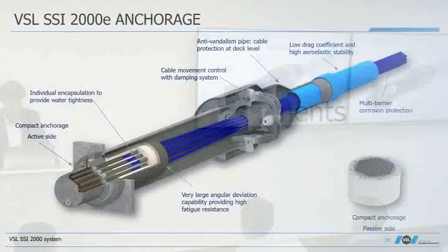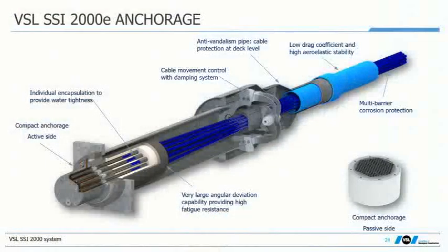Talking about anchoring components or elements. So this is basically the standard state-of-the-art technology of anchoring a cable to a structure. Two types of anchorage, one called the dead end, passive end, fixed end, depending on the vocabulary you want to use, and the other called stressing end or live end. Basically, you attach a cable with these two anchorage and you stress by the active one. You can stress by the passive one if you wish, but you cannot tune the force with the passive one. You tune the force by the active one.